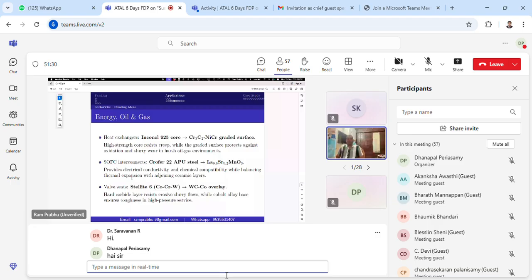Okay. The advantage of the ceramic is it has very good thermal resistance, very good tribological properties, mainly the wear resistance, erosion resistance, or corrosion resistance. So these advantages you can get from the ceramic. High temperature strength you can get from the tough core, and most importantly toughness and ductility you will get from the core. Okay, these are the prominent materials: Inconel 625 for the heat exchanger.